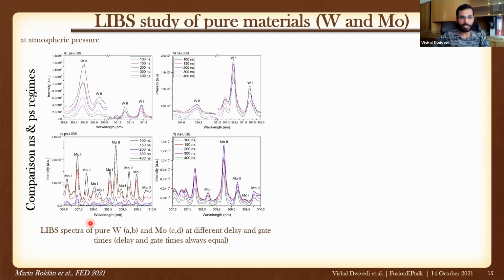We cannot accommodate full range spectra. We see nothing in the full range spectra, so we just cut down to show the difference between nanosecond and picosecond. And we can see the narrower lines obtained in the picosecond LIBS for molybdenum and also for tungsten, for different delays, 100 to 400.